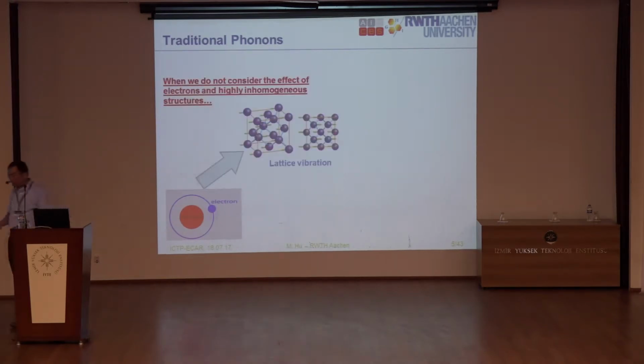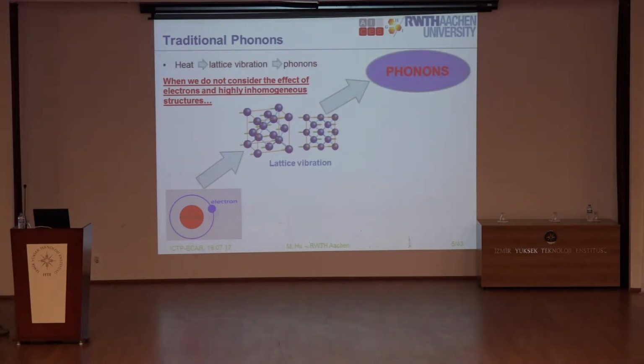And then if you use a simple idea of the lattice vibration, if you just remove the contribution of electrons, you can get the traditional definition of phonons, because once you take out the electrons, you do not consider the effect of electrons, and everything left is just this lattice. And then due to the temperature effect, the lattice will vibrate, and then we have the language of phonons, and you have different modes and mode conversion, and also phonon scattering, the phonon gas model, and so on, right?